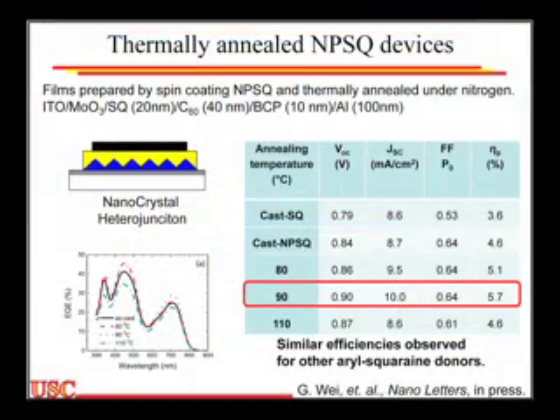Now if we anneal this one, we start with a film of the alpha naphthophenyl squaraine derivative. I start annealing it, and I'm only showing 3 temperatures here. We looked at a wide range of them: 80, 90, and 110 degrees. You can see that, the dashed lines don't show up so great, but at 90 degrees is where we get the biggest EQE. That is to say, we get the biggest enhancement of the efficiency that we see.